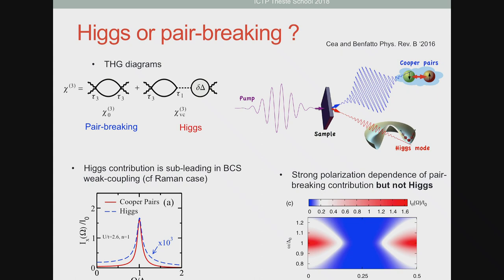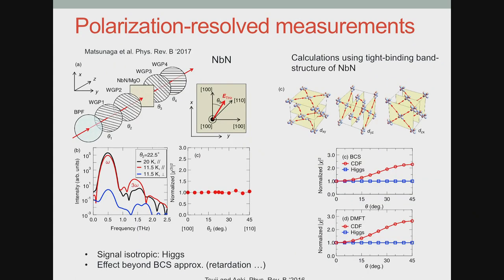So in the case of just a tight binding model with only nearest neighbor hopping, the pair breaking contribution vanishes when you excite at 45 degrees of the axis, whereas the Higgs contribution is completely isotropic. So this tells you that maybe there is a way to disentangle these two contributions by looking at the polarization dependence of the signal. And this is sort of the puzzle. You can do that in niobium nitride, and what you see, to make a long story short, is that the third harmonic generation signal is essentially independent of polarization, completely, within a few percent. You hardly detect any polarization dependence.